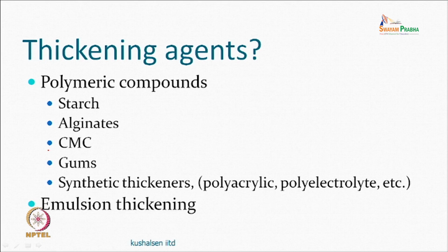A normal starch would be good at 10%, but you have hydrolyzed it to such an extent that the molecular weight has reduced, so you had to use more solid content. And why they wanted more is that it was believed that it is easy to wash; smaller molecular weight will come out easily, and the viscosity will be the same.